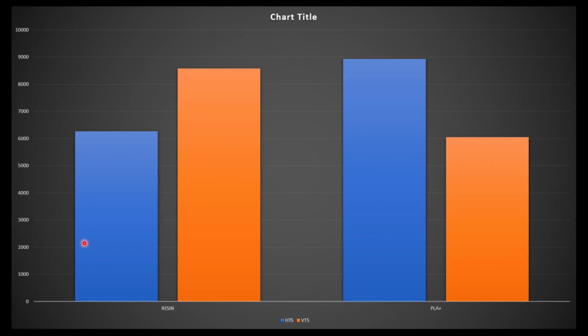Okay, now let's look at the data. So this chart right here is comparing the average tensile strength in PSI of the different samples we tested. Of each sample we had 5 different samples in each category here, each column. I just took the average of the peak force on each one, so the point where the plastic yielded, and I took the average force, calculated the tensile strength in PSI using the cross section, and this is the result. So resin is on the left, PLA Plus is on the right. The blue samples were the ones printed horizontally, and the red ones are printed vertically.